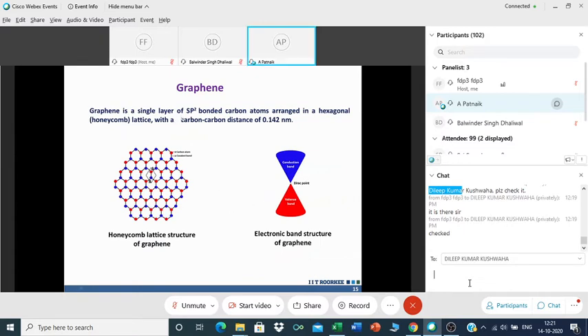It's a single layer of sp2 bonded carbon atoms, arranged in a hexagonal or honeycomb lattice form. You can see this particular diagram where the carbon atoms are arranged in a honeycomb lattice form, right? And with a carbon-carbon distance of 0.142 nanometer, the distance between two consecutive carbon atoms is 0.142 nanometer. And if you see the electronic band structure of graphene, it's a zero band gap material. Okay.